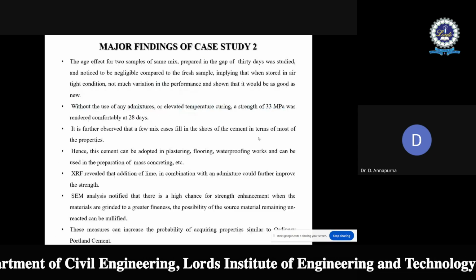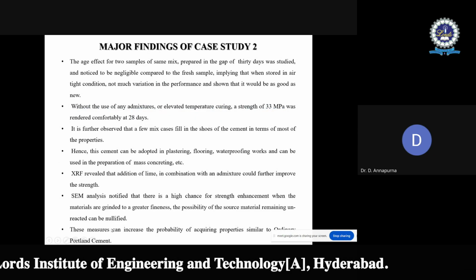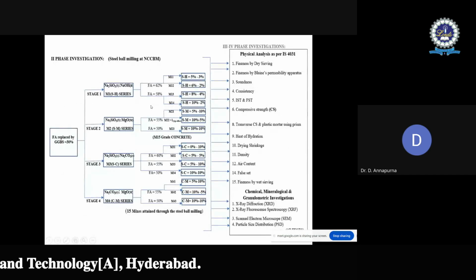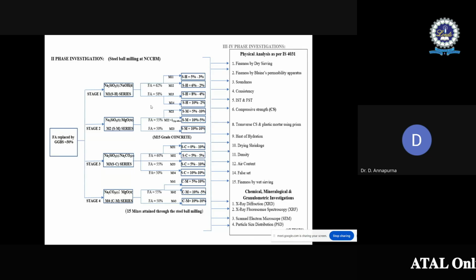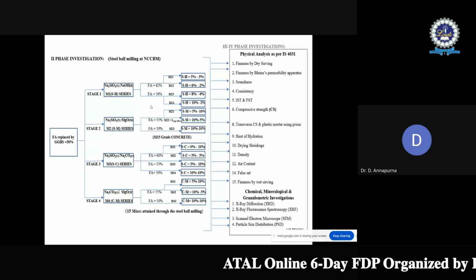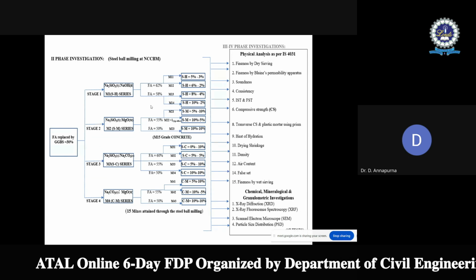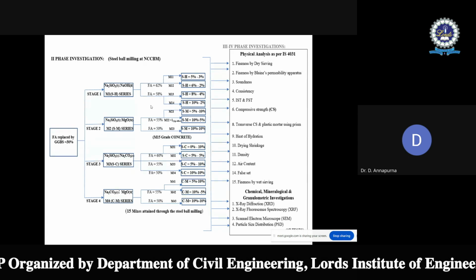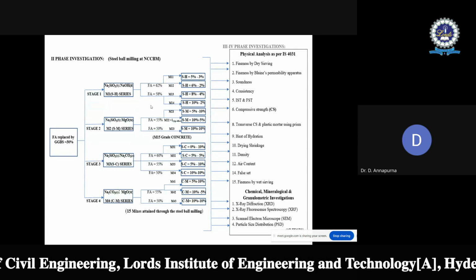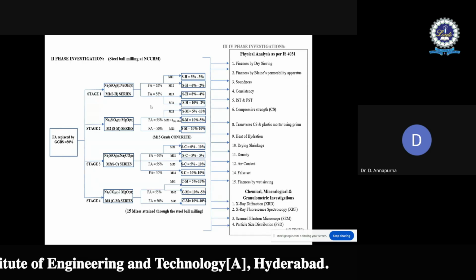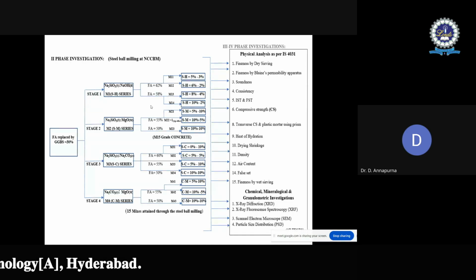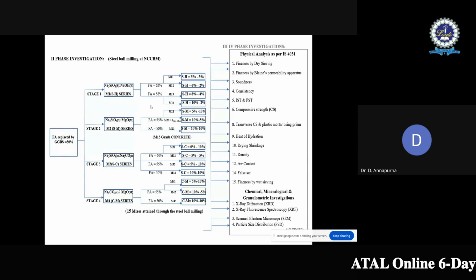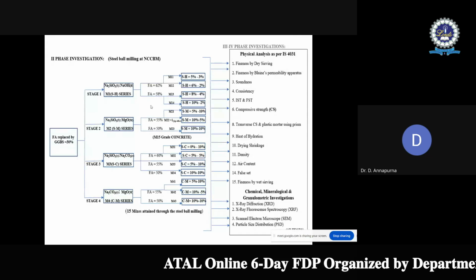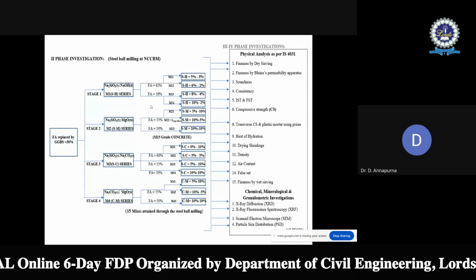So the major finding we got is that all the properties of this geopolymer cement are similar to those of ordinary cement, but we got the grade up to 33 grade only. We didn't get 43. As it is in the initial stage, we got 33 grade. So it has given encouragement towards progressing to get geopolymer cement or alkali activated cement of 43 grade. Even in the near future, we may get 53 grade geopolymer cement or alkali activated cement also.